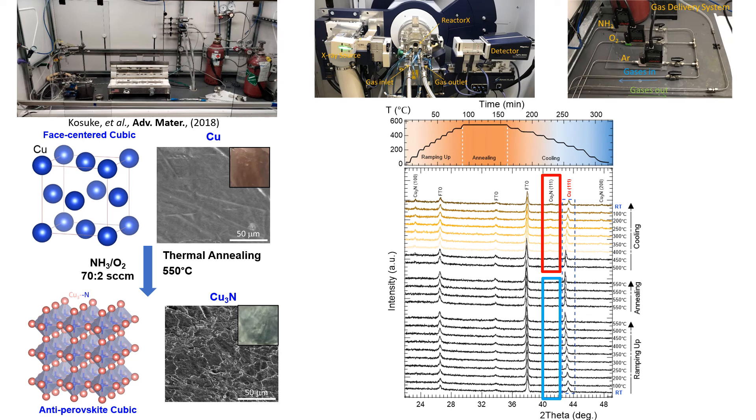Interestingly, we noticed here that the material isn't actually formed as we heat up to 550 C or soak at 550 C, but rather forms as the material cools down to 450 and 400 Celsius. Using a thin film copper sample of 200 nanometers, oftentimes we could see metallic copper at the back contact with green copper nitride on top. This got us thinking that if we thermal cycle the process between 450 and 550, for several loops, we can convert more of the metallic copper and improve the material quality.